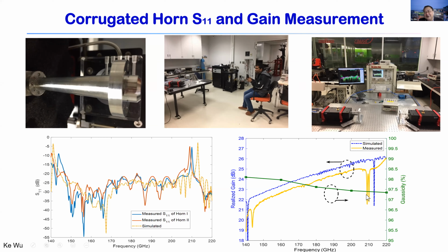There's a slight deviation, but the efficiency is still very good. You can look at the efficiency over the frequency range of interest; it is quite flat, about 98%.